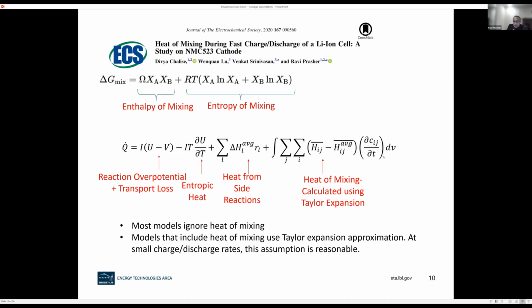I'm not going to bother you with the equation here, but just look at here. One is a reaction overpotential and a transport loss just because of finite electrical conductivity, finite ionic conductivity. So you can consider this as Joule heating as well as the reaction overpotential. Then entropic heat, which is basically reversible. Then heat from side reactions, as it is a chemically reacting system. And there's something called heat of mixing, right? Which comes from enthalpy of mixing.